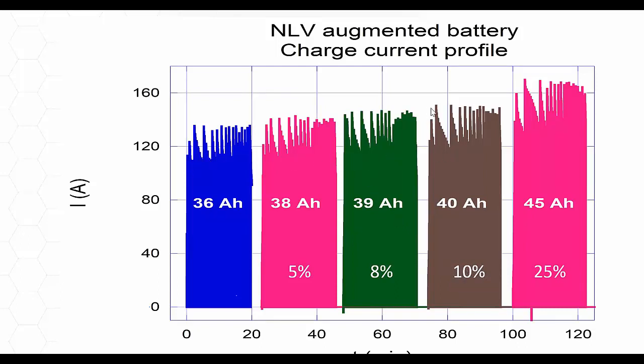And you can see here that the current profile is different in each case, all right? And we even pushed the limits to 45 ampere hours. So we were able to add 25% of the energy in the same cell without changing the chemistry of the cell. It's the same cell, and we could actually extract 25% more energy from that cell. So this is what we call augmented batteries. Only by changing the way we charge the battery, we can add energy to the battery. That's okay. So this is counterintuitive, because when Samsung tells us their cell is only 3,000 milliampere hours, we have done a test today. We could extract 3,600 milliampere hours from the cell.